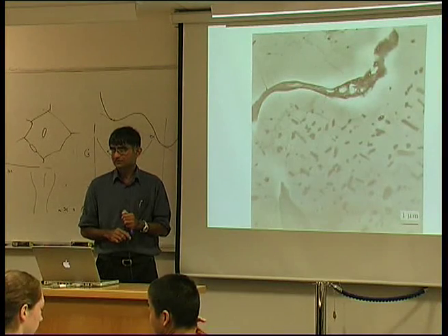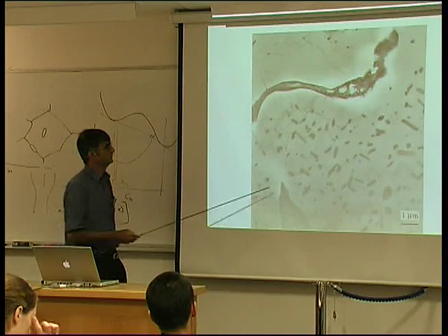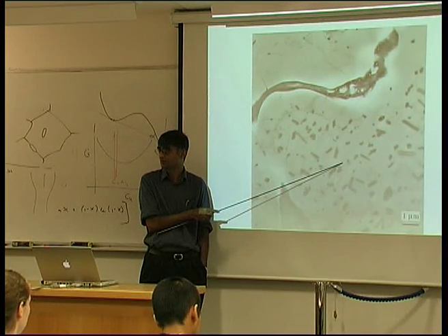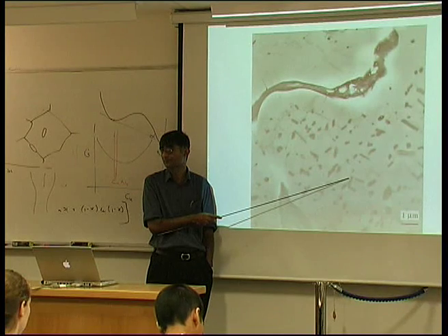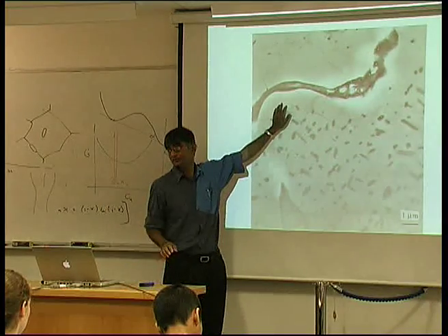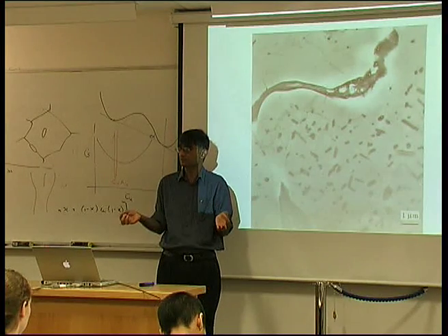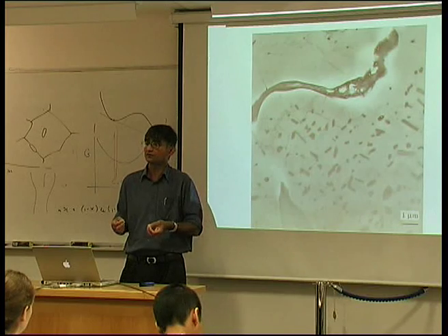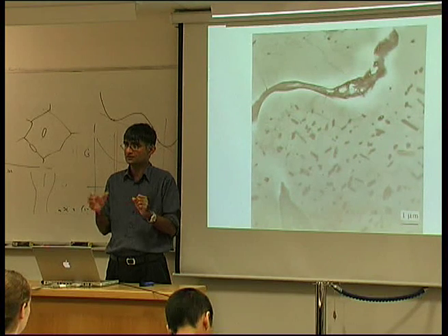Okay. Now, if I go back to this slide, the other big problem with having precipitate-free zones is that the chemical composition here can be different from the chemical composition in the matrix. So you have different electrochemical properties in that zone compared with here. And that means that you focus corrosion in this narrow region. Okay, so you have a large cathodic area and a small anodic area. And the corrosion current density will be much higher in this region than in this region. So precipitation hardened aluminium alloys containing precipitate free zones are very susceptible to localized corrosion.